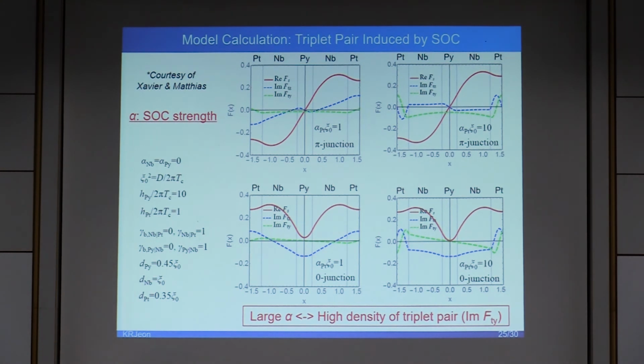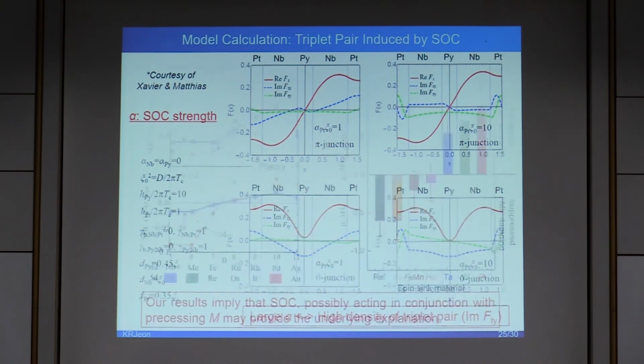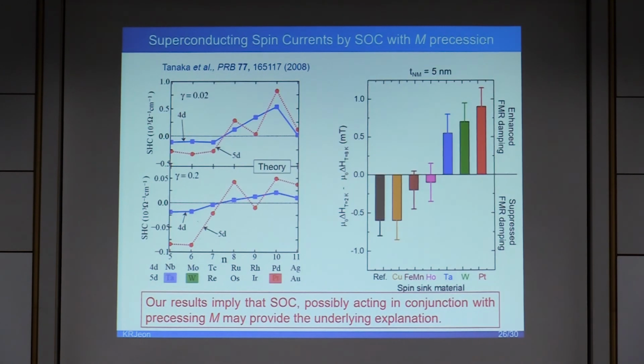reproduce our result, our experiment on other materials shows that 5d heavy metals with strong spin-orbit coupling reveal a large enhancement compared to the other light elements. This suggests that spin-orbit coupling, possibly acting in combination with precessing magnetization, may provide the underlying mechanism.